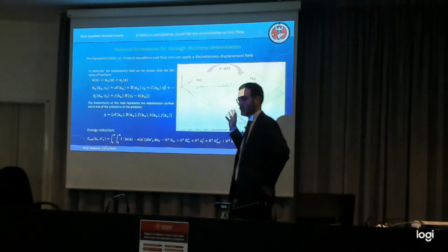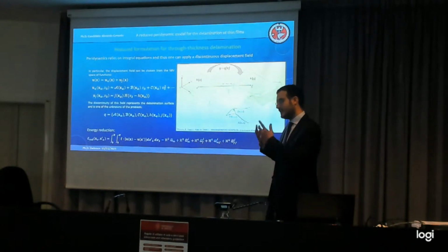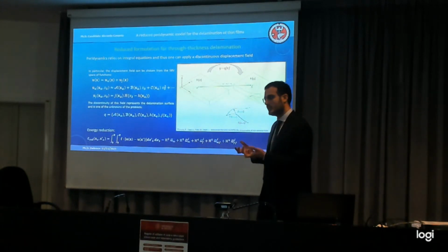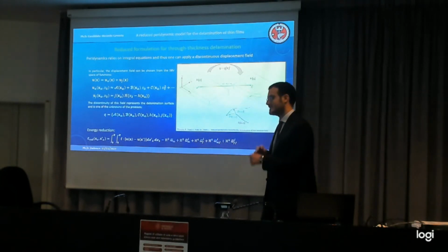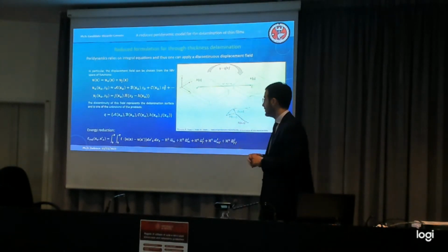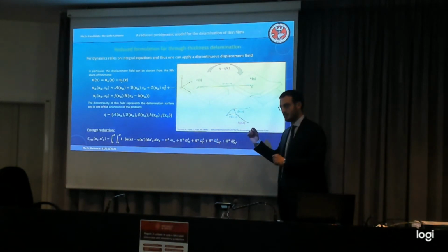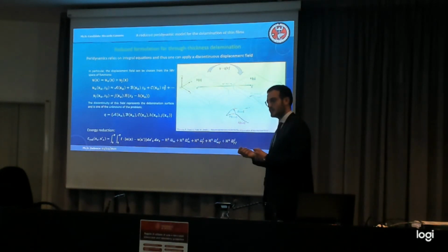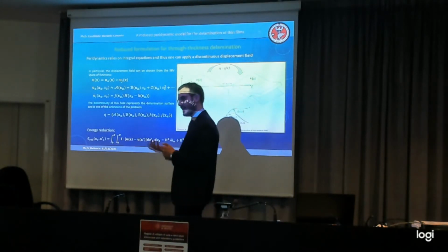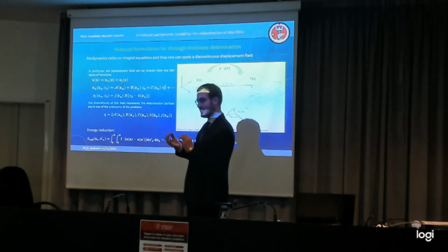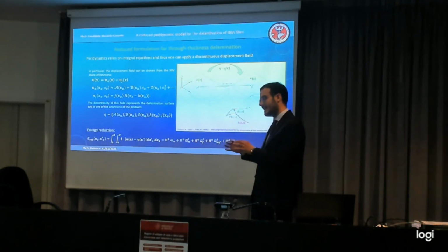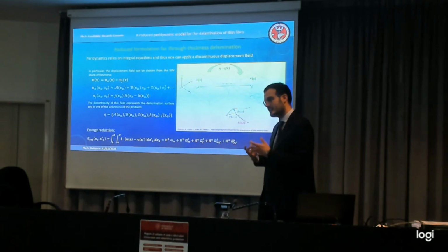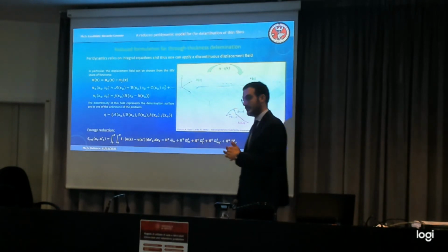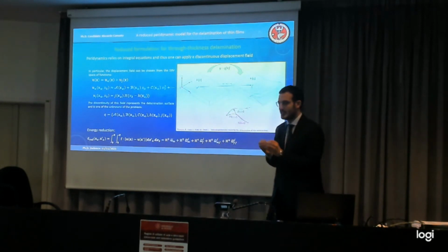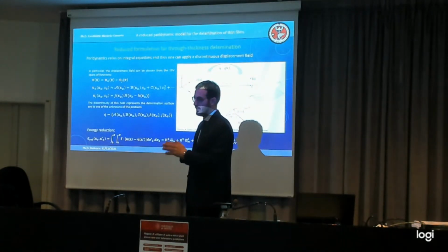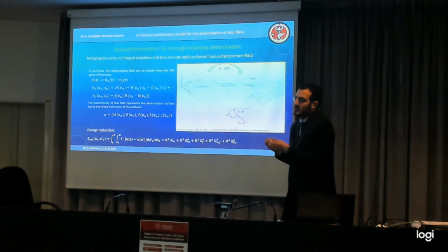So I would say yes, it's possible to treat anything, but it very much depends on the type of loading, because the model is very sensitive to minimal differences. As you've seen, the damage function in the strain energy is a continuous function, so the degradation is progressive, and the minimal mistake can lead to crack propagation beginning and developing where you don't want them. So it's very hard to tune the model, and each and every case needs to be treated separately. But the theory in principle is very clean.